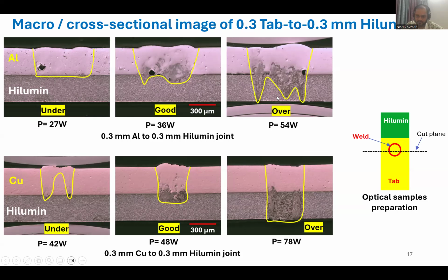Why is this overweld? Because you are penetrating the bottom sheet by 100%. This is definitely not good, because after some cycles, you may have seen, there is electrolyte leaking, because there must be micro pores for the electrolyte to flow from this channel to the outside. So this is not recommended for our purpose in a battery. Not only electrolyte leaking, this is also transferring heat to the inside of the cell, which can cause potential aging of the cell. So this is an example of aluminum to Hilumin. This is an example for the underweld, good weld, and overweld. You can easily identify which is under, because this is not sufficient penetration. This is good weld and this is overweld.